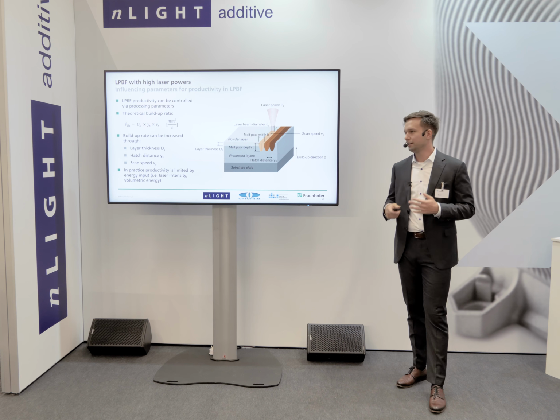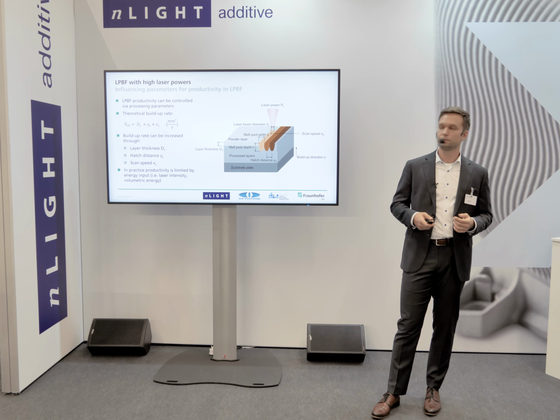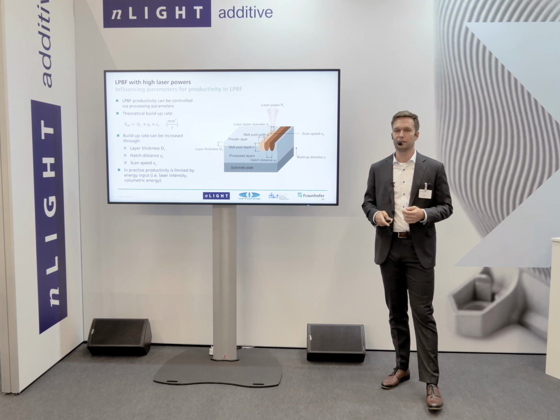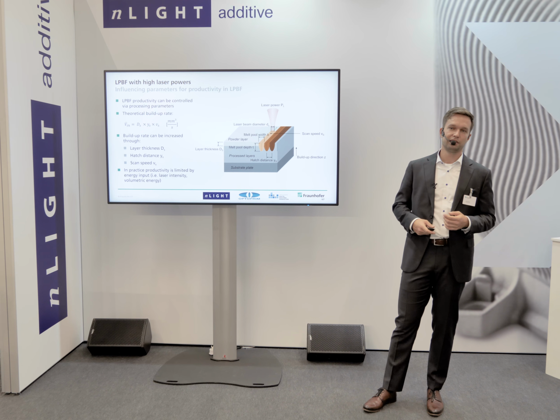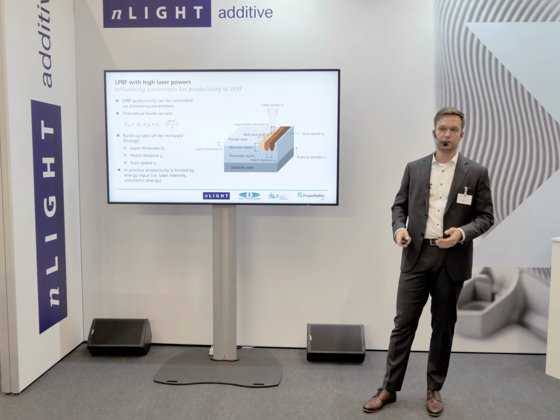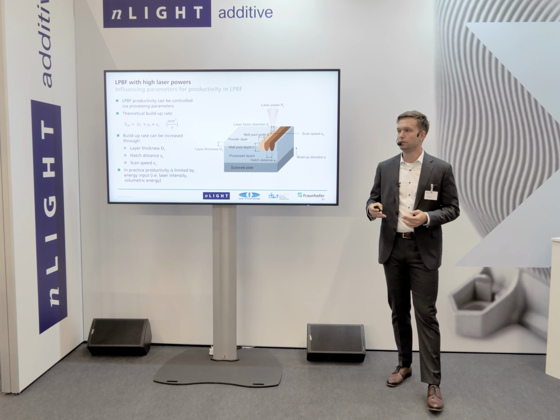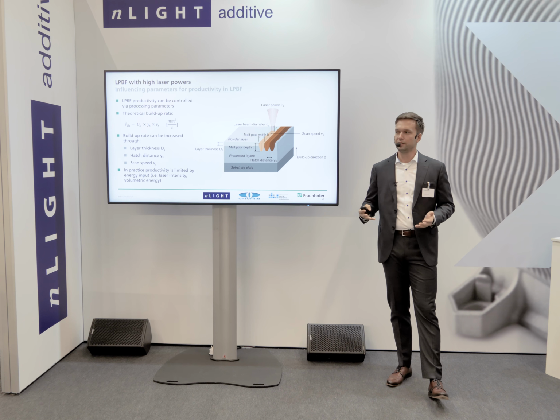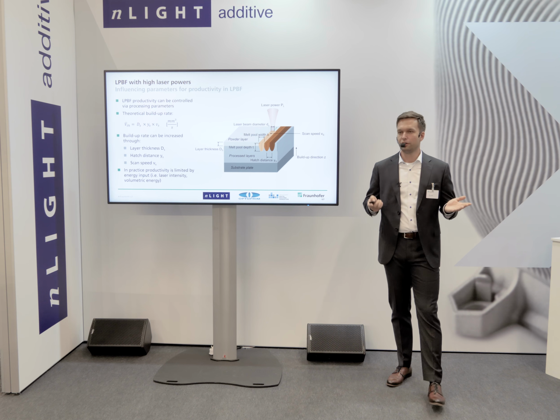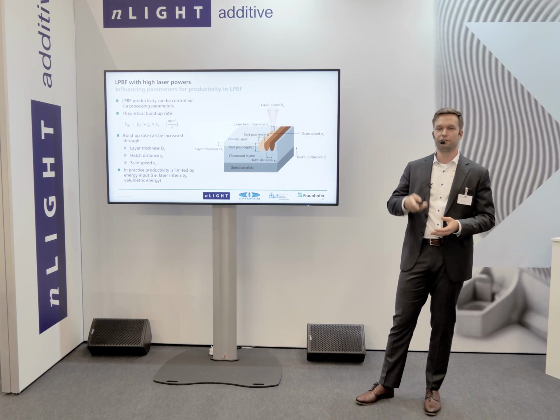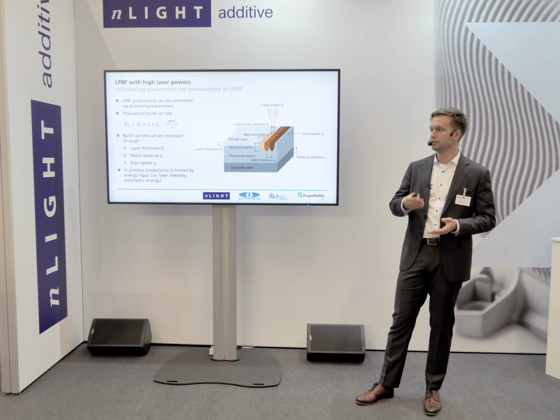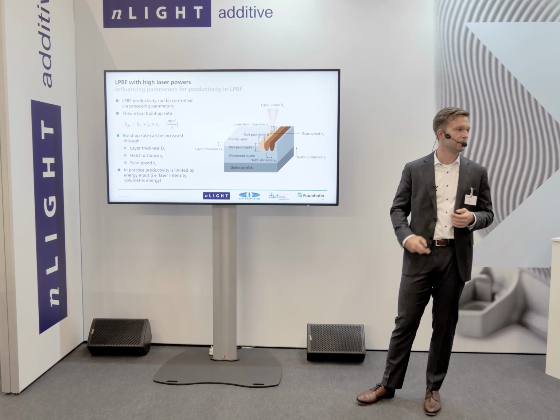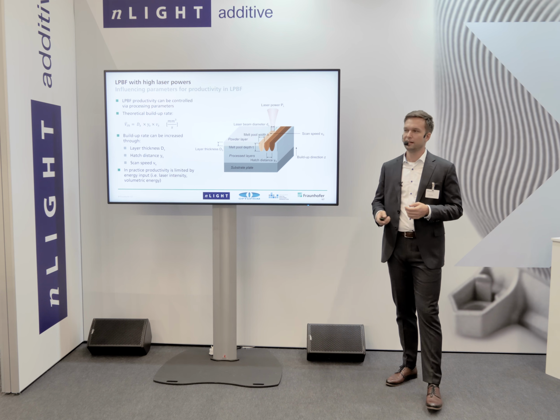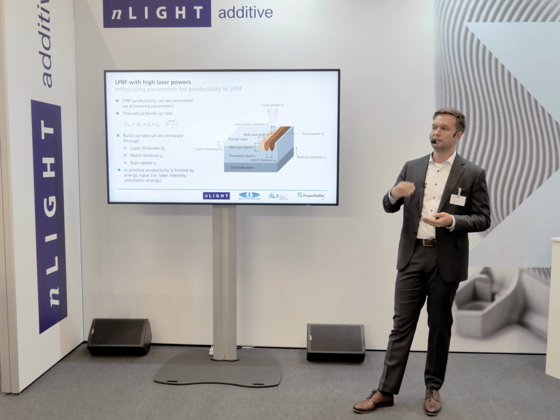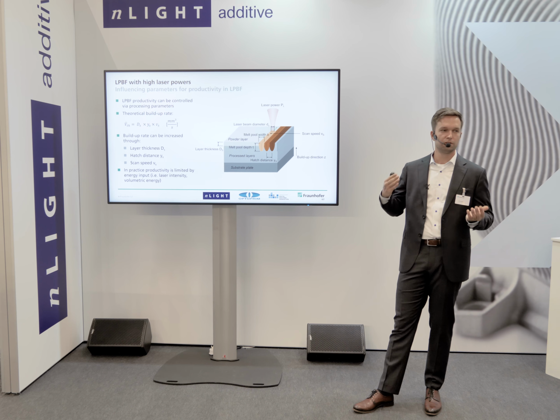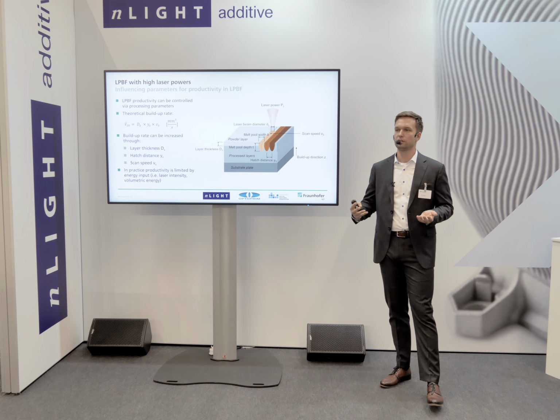The build-up rate, at least the theoretical build-up rate in L-PBF, is mainly defined via the processing parameters, namely the scan speed, the layer thickness, and the hatching distance. So in principle, to scale up the productivity, you need to enhance these three parameters to get as productive as possible. However, of course, there's a physical limit to that. You need sufficient energy input to fully melt the material and have no lack of fusion between layers and between several scan tracks. On the other side, there's also an upper limit, because at some point when your laser intensity gets too high, you will evaporate material and cause a lot of part defects.